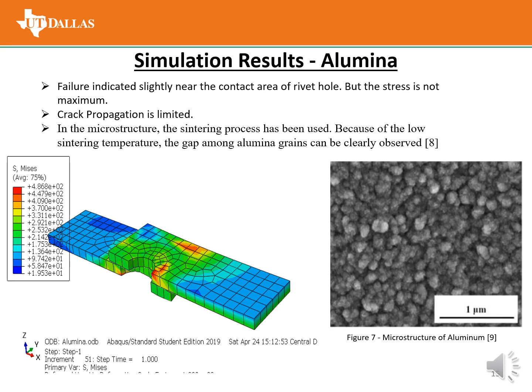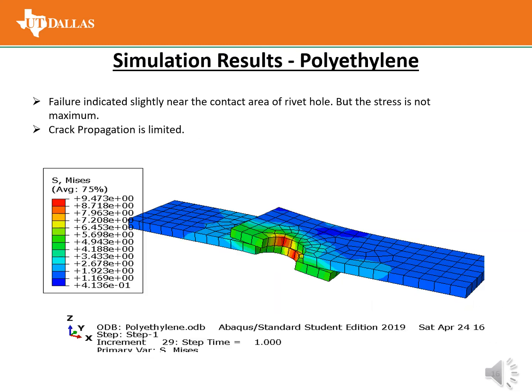For alumina, the failure is indicated slightly near the contact area of the rivet hole, but the stress isn't that much as compared to aluminium. If we look at figure 7, the microstructure, a low sintering process has been used, and the gap among alumina grains can clearly be observed. For polyethylene, failure is indicated again near the rivet contact, but the stress isn't near maximum, and the area away from the rivet contact does not face high stresses.